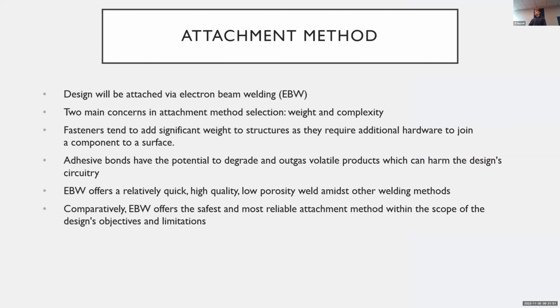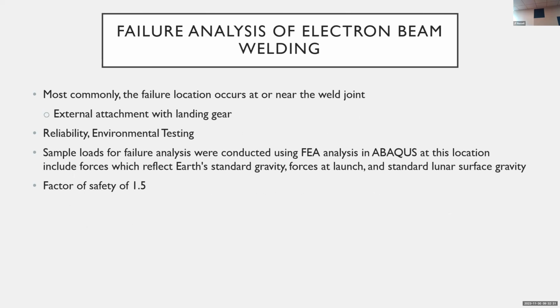Our design will use electron beam welding, or EBW, as its main attachment method. Compared to fasteners and adhesive bonding, this provides the most reliable and least hazardous attachment method. Fasteners tend to add a significant amount of weight and complexity to integrate into our design, and adhesive bonding tends to outgas volatile products due to the continuous radiation exposure and just through general fatigue. Additionally, EBW was chosen amongst the other welding methods mainly due to the time efficiency, while still producing a high quality, low porosity weld that's free of contamination.